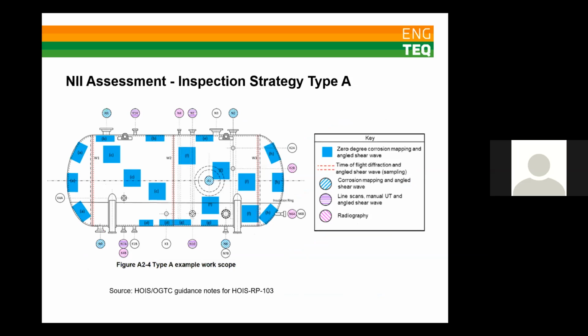So this is a typical example of a standard type A inspection, and this is taken from the HOIS guidance notes. So typically you would be inspecting 5 to 10% of the surface area. The areas selected are spread throughout the vessel. So remember that no degradation is expected in this case. So we're looking to confirm the absence of degradation in all locations throughout the vessel. One thing to point out is that there's a higher coverage at the nozzles.